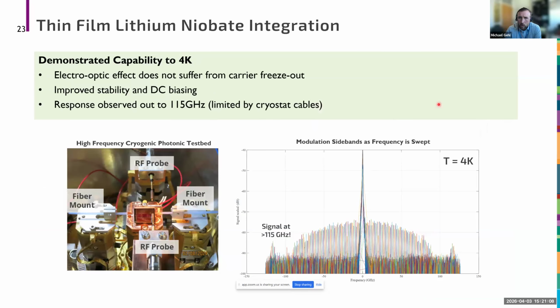And so we've qualified these devices at cryogenic temperatures as well. So this is an example of that chip being tested in a photonic cryogenic test setup. And in this case, what I'm showing on the right here is just an overlay of multiple optical spectrums where we applied an RF tone, looked at the sidebands from that modulation, and then stepped the RF frequency. And you can see the amplitude of those sidebands begins to fall off, mainly due to the cabling within the cryostat. But even with that fall off, we were still able to see operation out beyond 100 gigahertz with these devices, all at 4K.